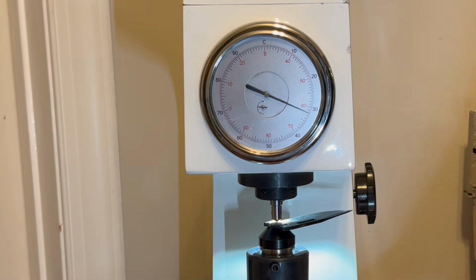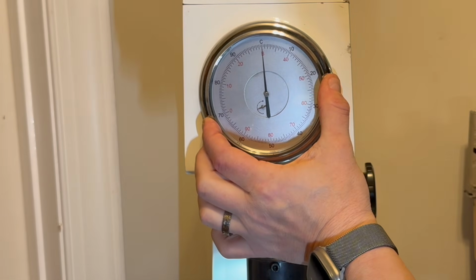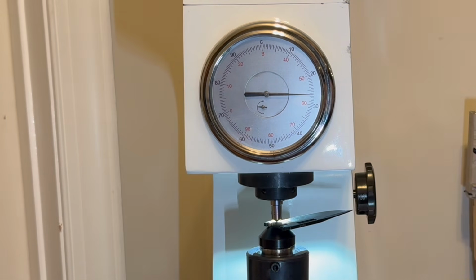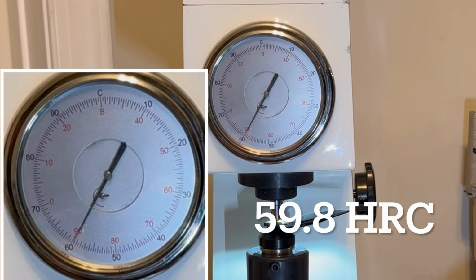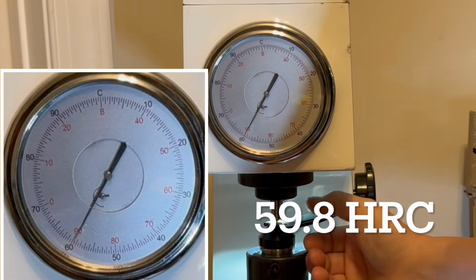PVD stands for physical vapor deposition or plasma vapor deposition, used interchangeably by folks in the trade. What I call it is not as important as the fact that the blade is subjected to 350 Fahrenheit temperature for about 2 hours. And here comes our first poke result, 59.8 HRC.